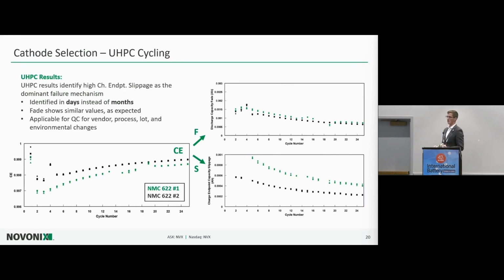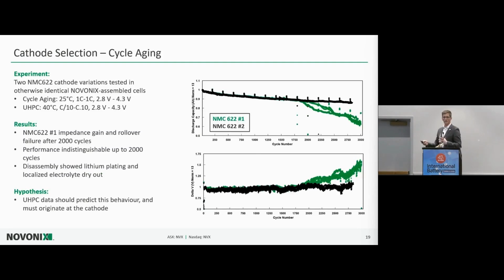The rate of relative reactions happening of these slippage-based mechanisms, electrolyte oxidation, transition metal dissolution, is twice as much in that other cathode. And even though we cycled these 25 times, we could see this just within a few cycles. The trick with this type of cycling, this method here, is we cycle these cells very slowly because we're looking at electrochemical contributions to failure, not necessarily kinetic. So these cells are cycled at C over 10. And this kind of removes any of these kinetic failure mechanisms from the picture. And we're really looking at what's the electrochemical difference fundamentally between these two cells that we've really controlled all these variables.